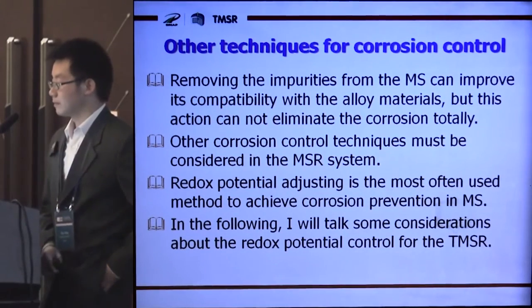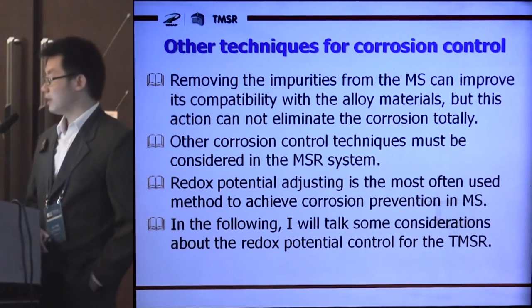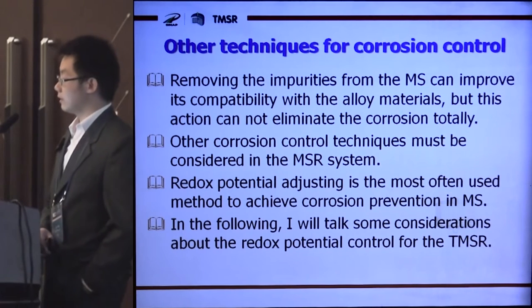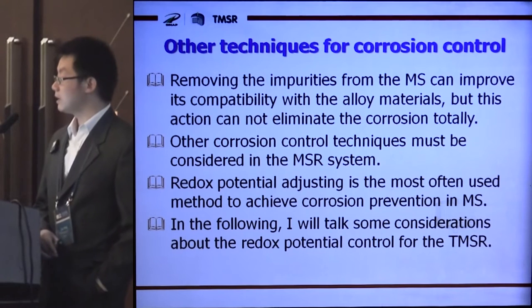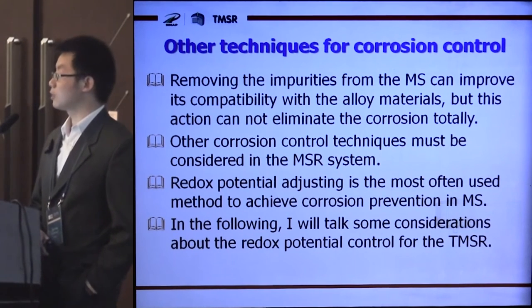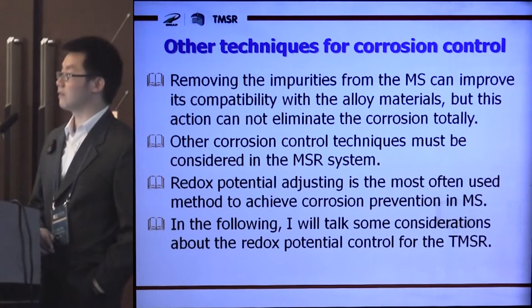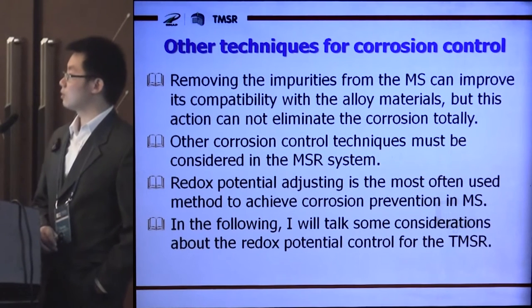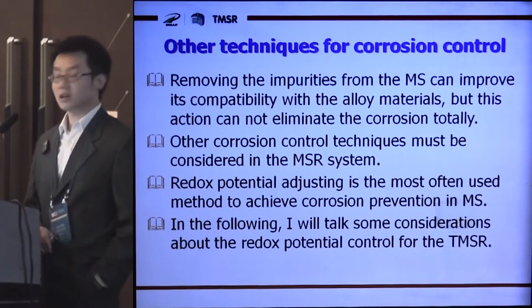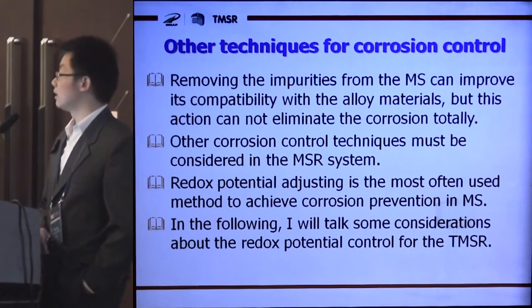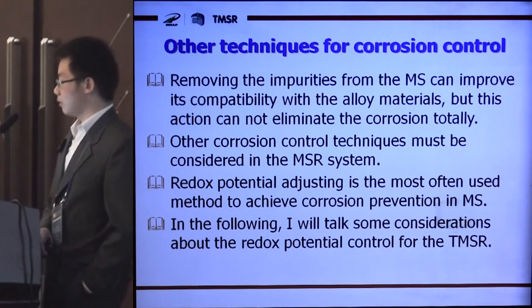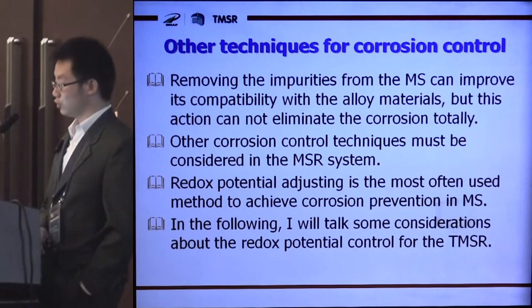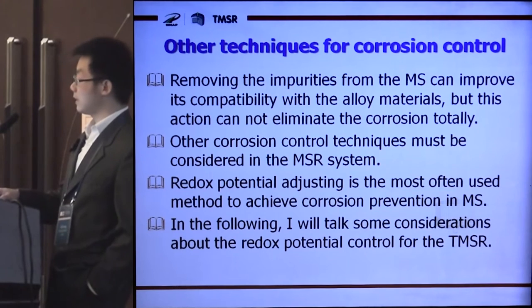Now we know removing impurities from the molten salt can improve its compatibility with the alloy materials, but this action may not eliminate the corrosion totally. Even if all of the impurities were removed, the corrosion reactions may also happen due to some other reasons, such as the oxidizing effect of nuclear fission or the air imported during loop operation. So some other corrosion control techniques must be considered in a molten salt reactor system. Redox potential adjusting is the most often used method to achieve corrosion prevention in molten salts. In the following, I will talk about some considerations about the redox potential control for the TMSR.